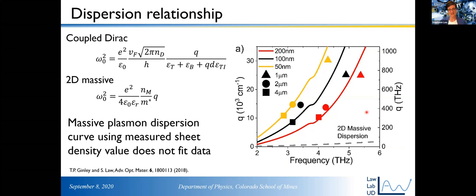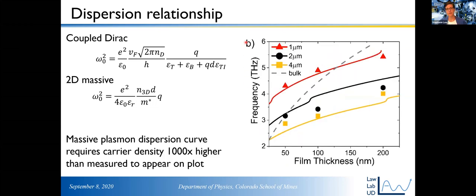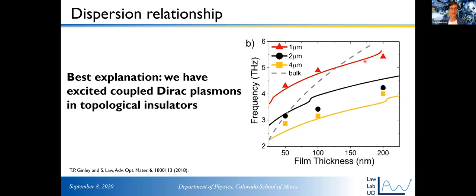But if you are not convinced by this, we can plot the data a different way. We can plot the plasmon frequency as a function of film thickness. And you can see, again, our experimental data agrees with the coupled Dirac plasmon dispersion pretty well. For the 2D massive plasmon dispersion, we had to multiply the carrier density by a factor of 1,000 to get it to show up on the plot. And even when it shows up, the shape is not right. The shape of the dashed line is nowhere near what we expect from our experimental data. So we're really quite sure that we have excited coupled Dirac plasmons in these topological insulators, and our experimental data matches the theoretical prediction quite well.